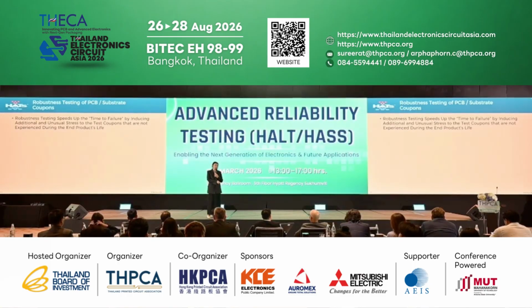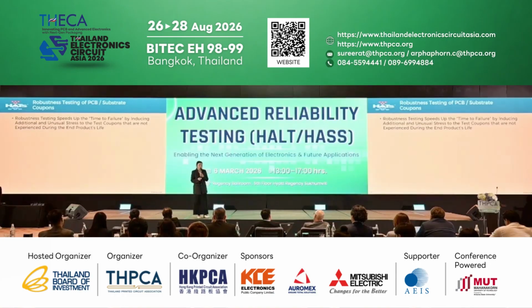It shortens the cycling from typically 1 per hour to 6 to 10 cycles per hour. So typically for 1,000 cycles, with a traditional dual chamber thermoshock chamber, you need 42 days to accomplish the thermoshock test. But with HATS2 coupons, with HATS test systems, we can accomplish 1,000 cycles in about a week. So all the research work is highly improved.